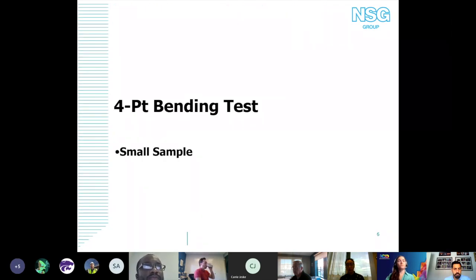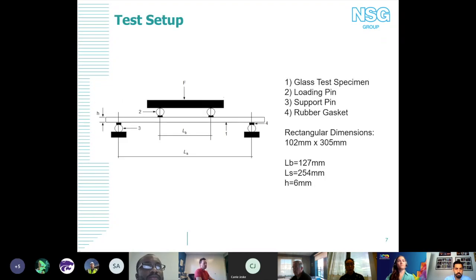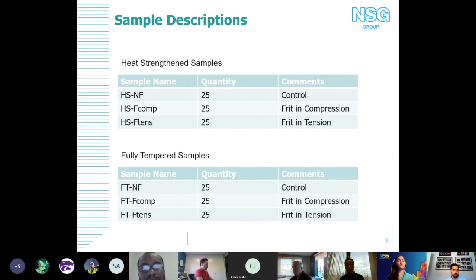Next slide. So we'll just start with the 4-point bend test. In these, they were really small samples, about yay big, handheld. But we did 4-point bend test. So essentially your maximum stress would be the entire area between your top 2 loading pins. That way we knew it was always fracturing at a location of maximum stress. So we tested heat strengthened and fully tempered lights. In these, we had our uncoated controls, and we tested with the frit in tension and the frit in compression to see if there was any difference with regards to where the location of the frit was.